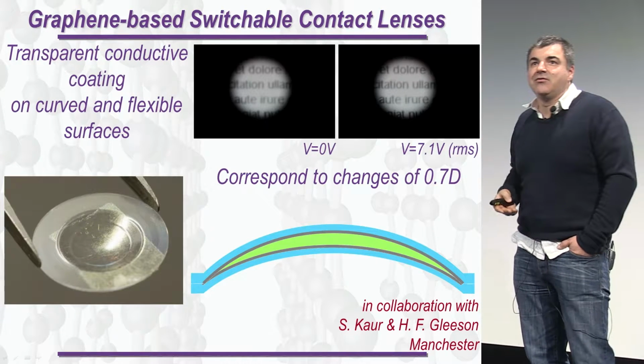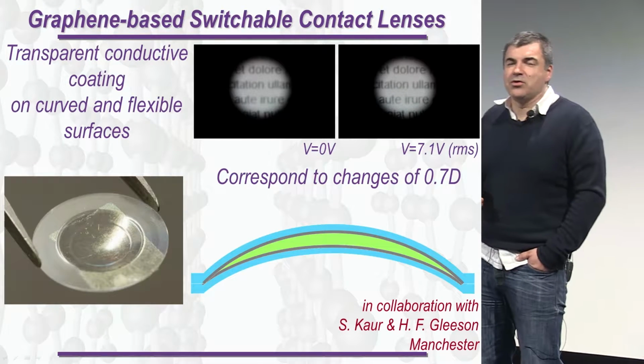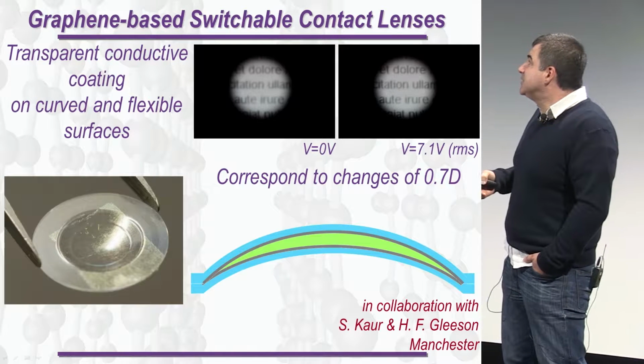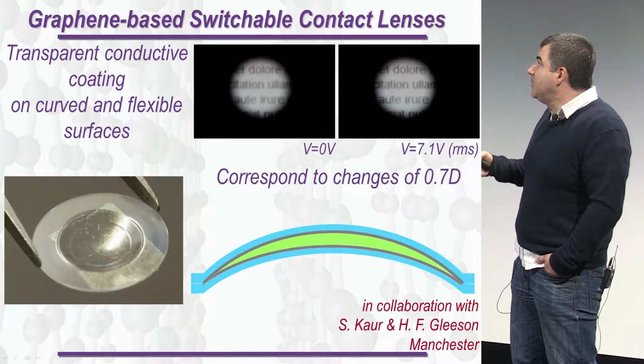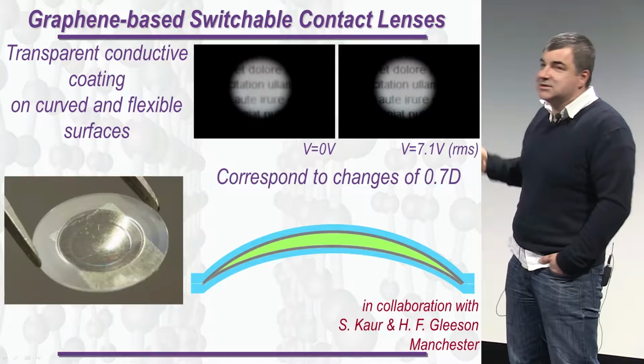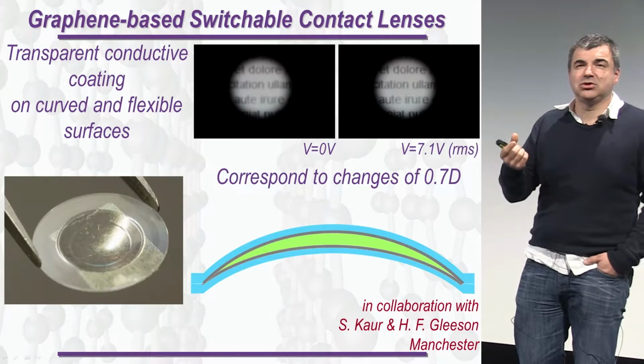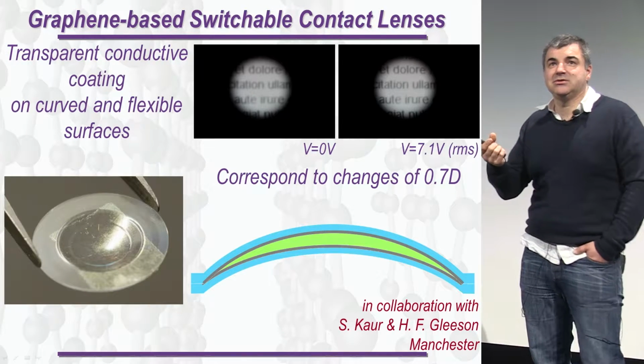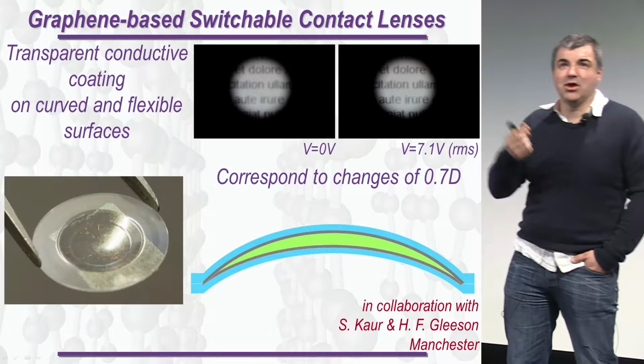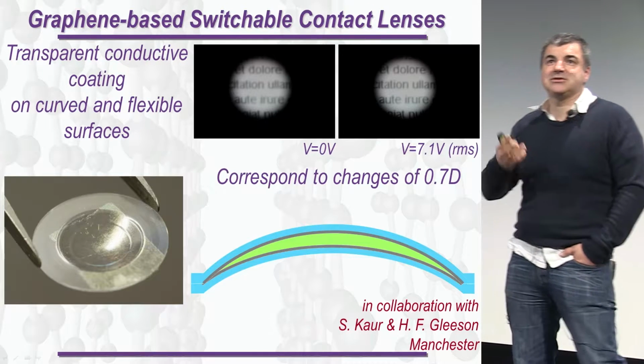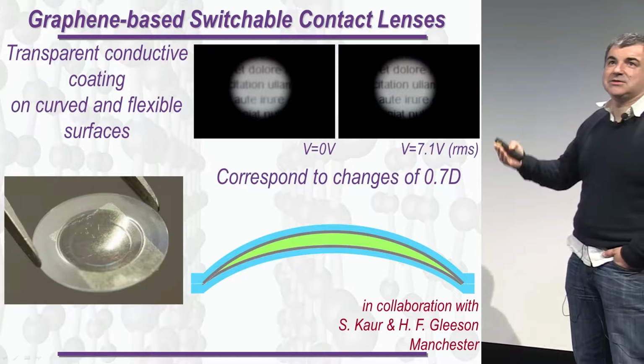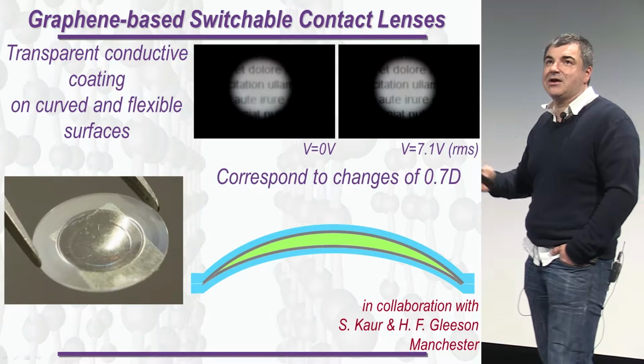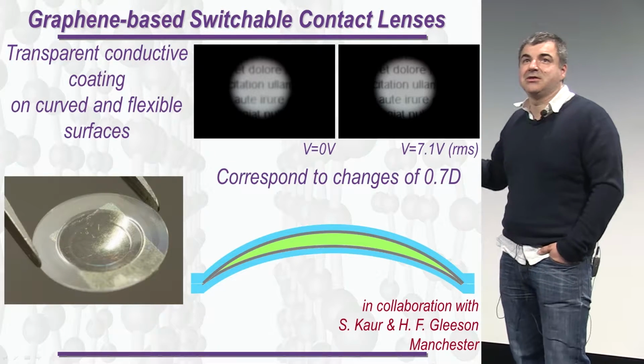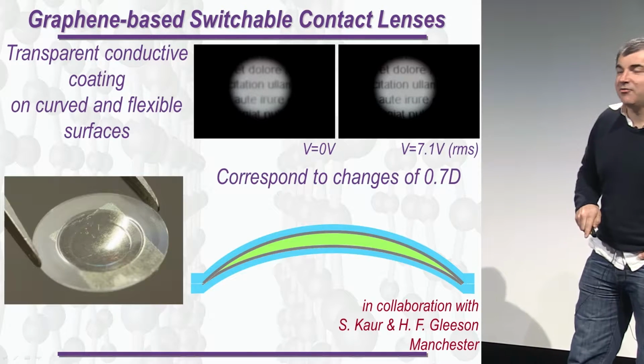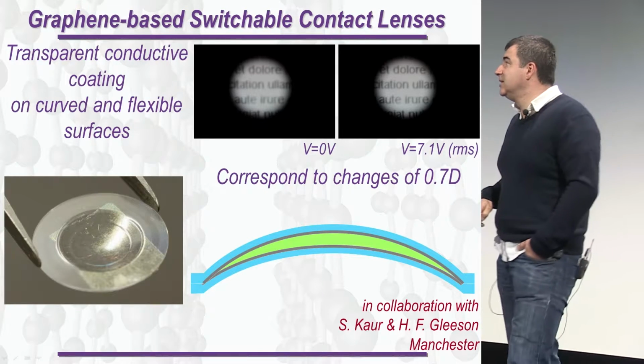That's what you need for your contact lenses. And because those contact lenses need to be curved and need to be flexible, the traditionally used transparent conductive coating won't work. It basically cracks and stops conducting. Graphene is very strong. It doesn't crack. It follows the surface. It works really well in this application.